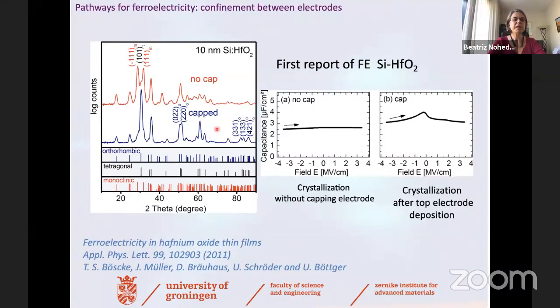But you could see from a powder diffraction pattern that indeed the two films were quite different, and they could associate the capped film with an orthorhombic phase that had been previously reported to be polar in zirconia. So since that moment on, when people see ferroelectric switching peaks in hafnia, this is assumed to be an orthorhombic polar phase that is known in hafnia.